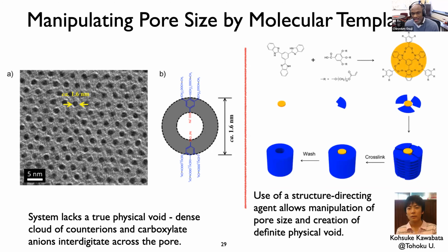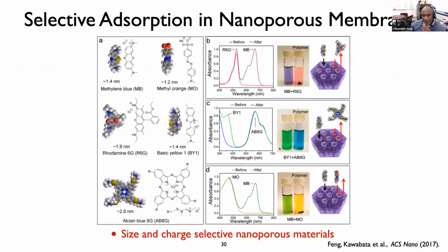And so we came up with the idea that we can create actual true physical voids in these systems by using molecular templates. So we could take a molecule like this propeller-shaped tribasic species and use it to guide or template the self-assembly of that gallic acid derivative, here shown as the acid form rather than the sodium carboxylate form of the molecule. We could form columnar mesophases, cross-link them, and then wash out that molecular template to provide a true physical void in the sample. And in fact, this works quite nicely.